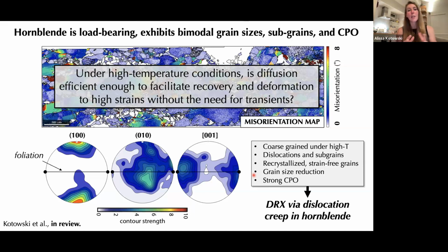What this means is that you have dislocation glide and dislocation climb and recovery to accommodate that dislocation in equals dislocation out requirement. So I think what this potentially means is that under high temperature conditions, diffusion is fast enough and efficient enough to facilitate recovery of dislocations. This allows the rock to deform to high strains, and maybe this means this rock does not need to make any slip transients to keep up. It doesn't need to make that mechanical mistake, that slip transient, to deform to high strains.